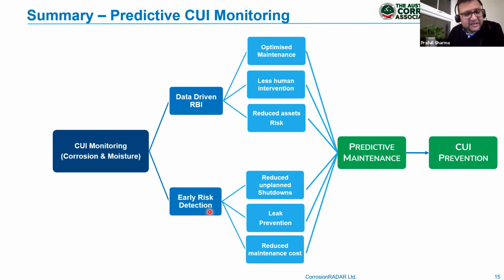This is still early risk detection leading to reduced unplanned shutdowns, predictive maintenance, and finally CUI prevention, because some of the asset owners, especially Norway, Europe, they're starting to say that it's better to prevent rather than inspect. Prevention is normally done through coatings or better insulations, but if we know that there's a wetness going on inside, then probably a prevention can be done by mitigating that wet condition, because so far the industry is struggling with water protection. There's only so much we can achieve with coatings and best practices of insulations. So this is more of an assurance additional monitoring tool, even for critical assets to achieve efficiencies.